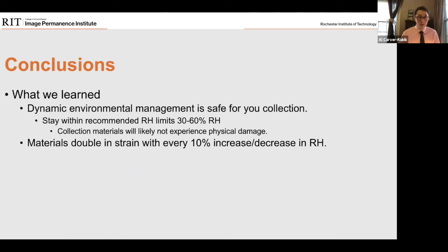So our conclusions. We learned some things which we can and cannot do with DIC, but I would say more importantly, we learned that dynamic environmental management is safe for your collection. As long as you stay within the recommended RH limits of 30 to 60% RH, you can implement this dynamic environmental management. And your collection's materials will not likely experience any physical damage within this range. If you exceed 60% RH, and if you go down to 20% RH, especially for a long period of time, you may see some damage, particularly if those objects have never experienced those highs and lows before.